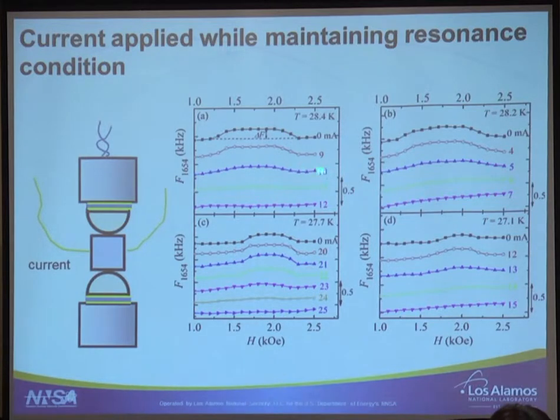Only when you get around 10, you start seeing this going down, and then by the time you get to 12 or even 11, this is totally flat. And you can see that the same phenomenology happens at all the different temperatures. It doesn't change until you get to the critical current, and then it becomes flat. You can see it a little bit better, or I can see it a little bit better.